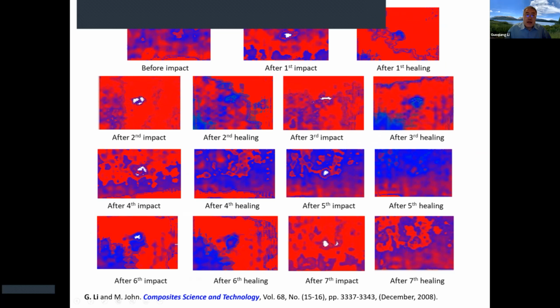Okay, so here is the shape memory polymer-based syntactic foam used as the core of a sandwich structure. You can see that this is the original structure. This is an ultrasound C-scan image. This is before impact. After impact, you have this damage zone. And then after healing, you go to a second impact, second healing, all the way to the seventh impact, seventh healing.